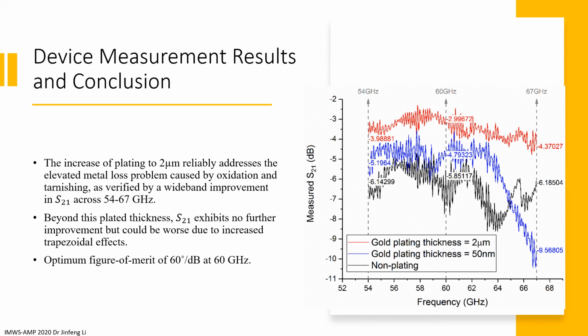The increase of the plating to 2 microns reliably addresses the elevated metal loss problem caused by this oxidation and tarnishing, as verified by this wideband improvement in the S21 across 54 to 67 GHz. It is experimentally verified that 2 microns can suffice to reliably deter the copper oxidation, while degrading S21 by only 0.1 dB compared with a bare copper-based device simulation, assuming no oxidation. Beyond this plating thickness, S21 exhibits no further benefits, but could be worse due to the increased trapezoidal effects. Our optimized device reports a figure of merit of 60 degrees per dB at 60 GHz, which is a significant improvement of 42 degrees per dB compared with other people's work.